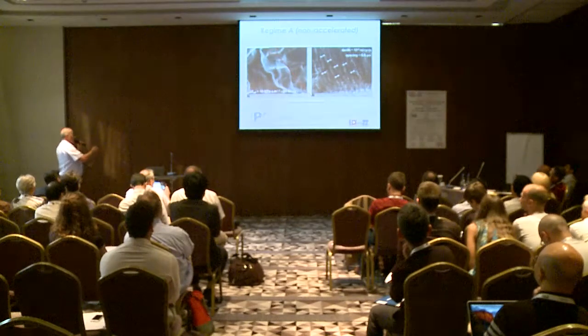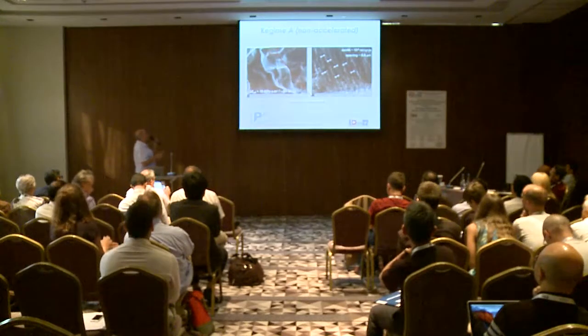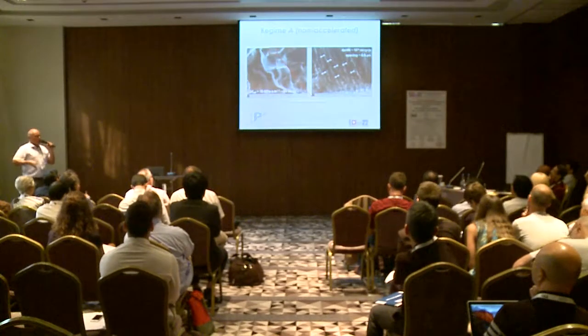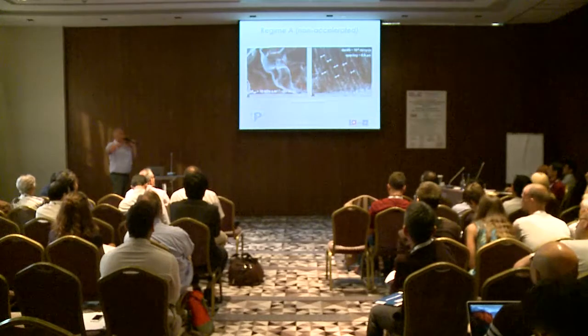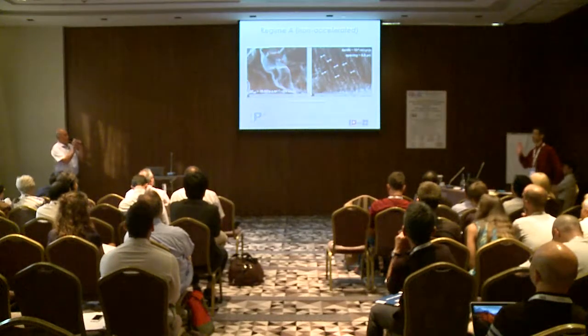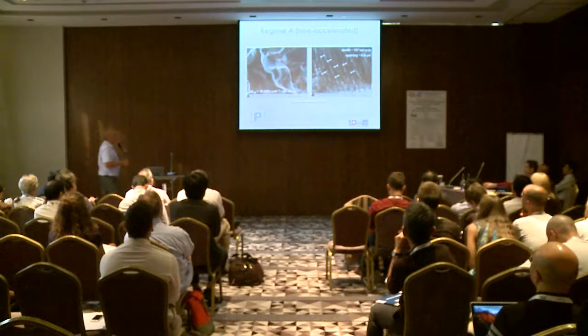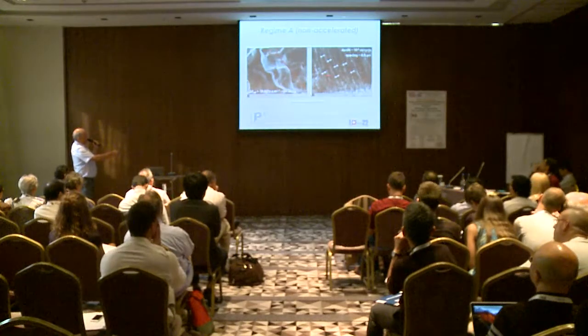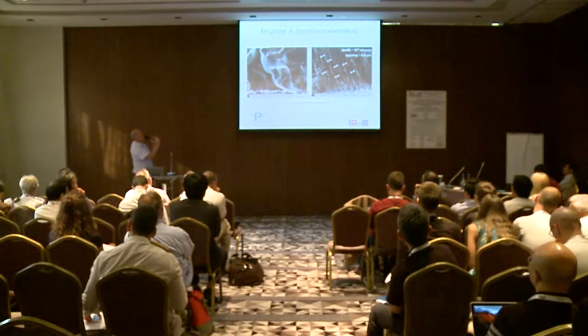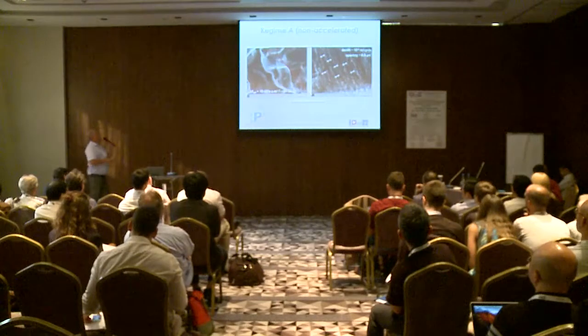And if we look at higher magnifications on these intergranular facets, we can notice the presence of some kind of stripes, with only one system of stripe for a given facet. And the stripes are more or less perpendicular to the crack growth direction. This is a higher magnification view of these stripes, and you can see that on the given facet, you have more or less a constant spacing. In that case, it could be 0.5 micron.